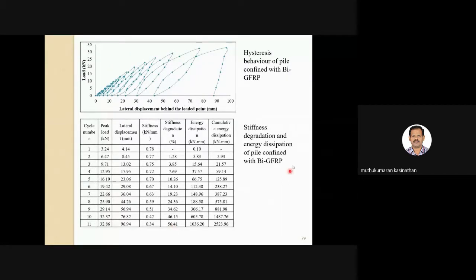Whereas the glass fiber in the bidirectional arrangement is almost close to the longitudinal arrangement, because you know that in the bidirectional arrangement, the circumferential arrangement is ineffective, whereas the longitudinal arrangement is effective. With a pure longitudinal arrangement, we have gone up to the 12th cycle, whereas the bidirectional arrangement is almost close to the longitudinal arrangement, with 56% degradation on the 11th cycle.